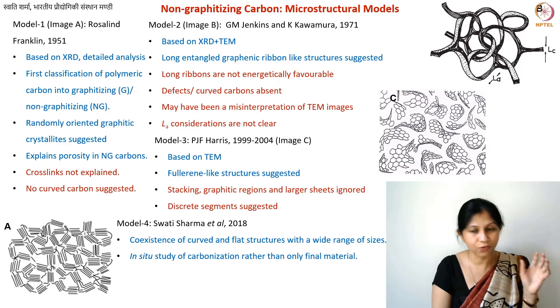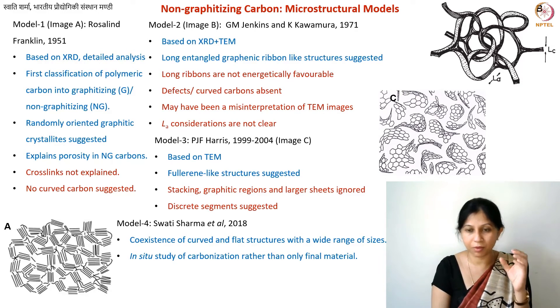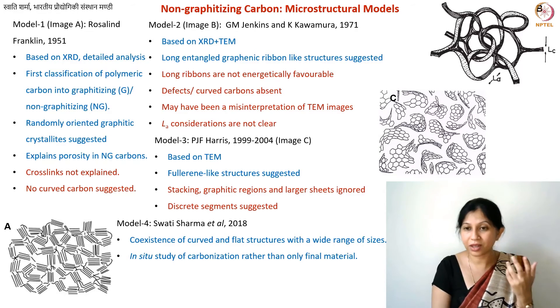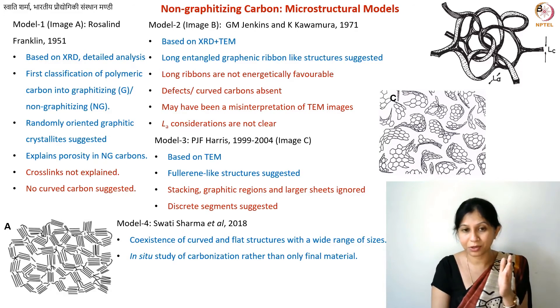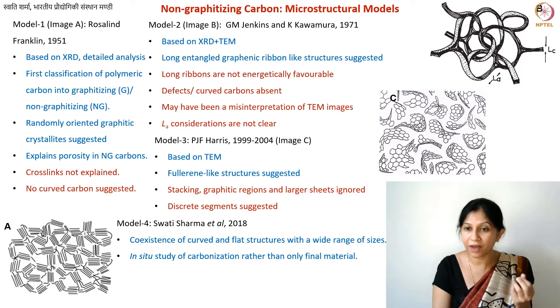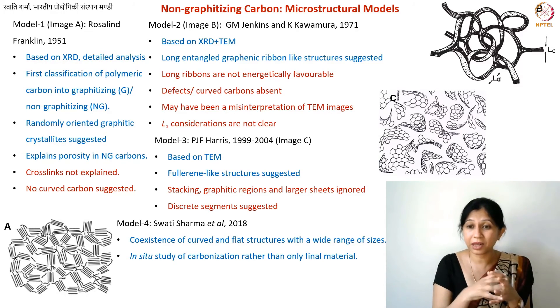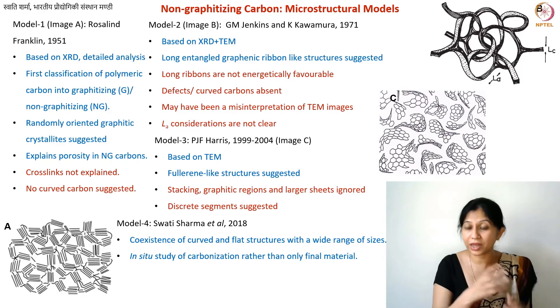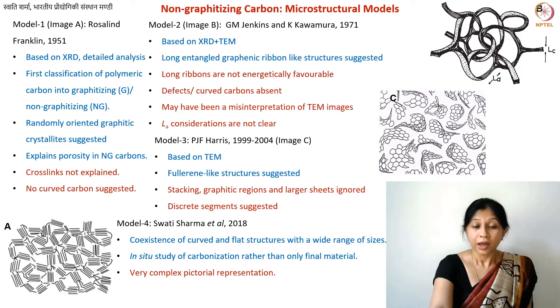When looking at the process while increasing temperature, you can see the effect of each temperature increment — seeing the entire process rather than just the final material. Also, when you have only the final material, sample preparation for TEM requires extremely thin samples, and during preparation itself you generate stresses that would not occur in in-situ studies. The one major limitation, as I mentioned, is that this model has a very complex pictorial representation.